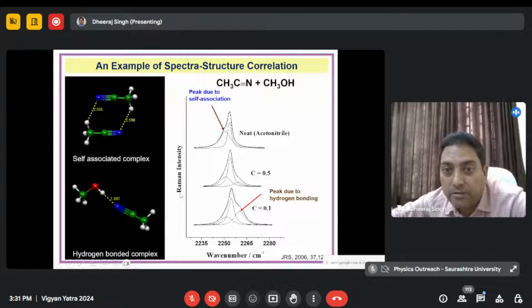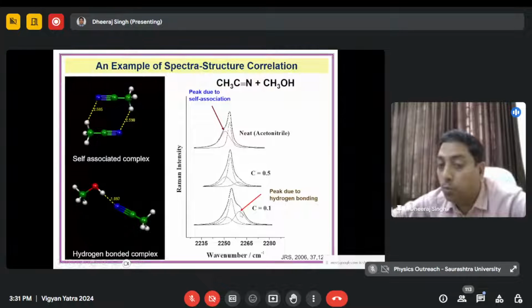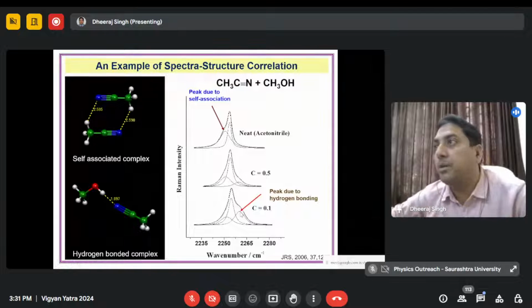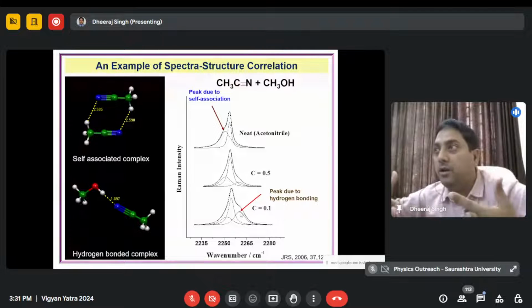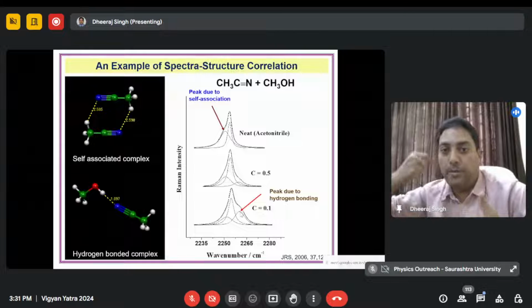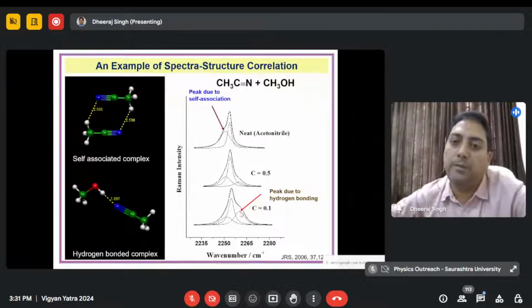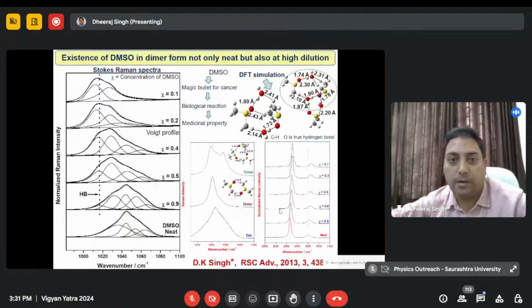Means the intensity variation you can see here on the right-hand side: in neat acetonitrile there is no peak, but after mixing the methanol a strong hydrogen bonded peak is coming. This shows that without seeing the molecular structure we can predict that the C triple bond N binds by hydrogen bond to the methanol molecule, and this is clearly visible in that particular Raman spectrum.